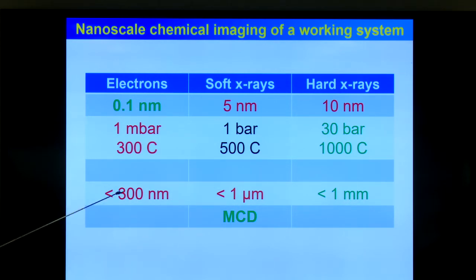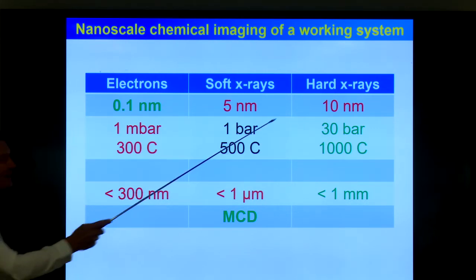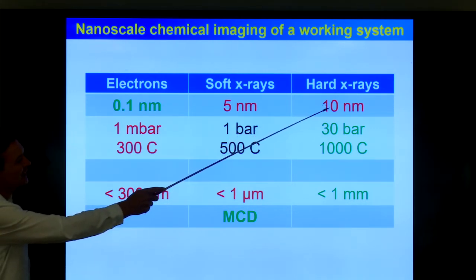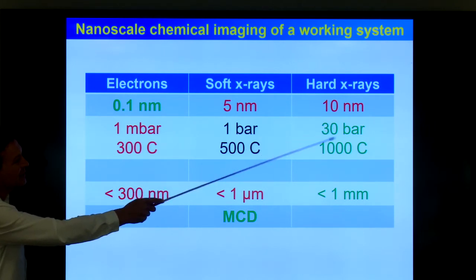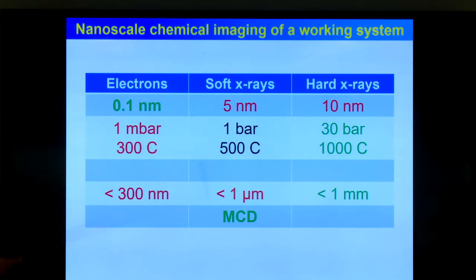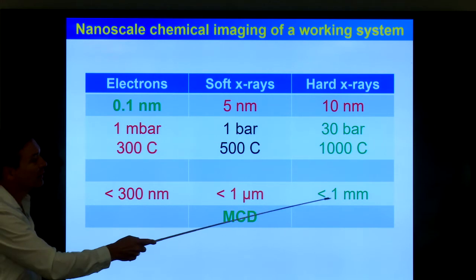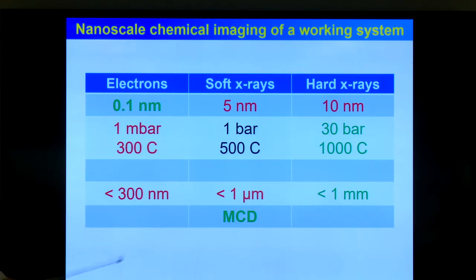So for catalysis, most experiments will be done with hard X-rays, because the resolution is 10 nanometers. You can go to any pressure and any temperature you like, because it's now hard X-rays. And the sample can be macroscopic, so you can do real catalysis.